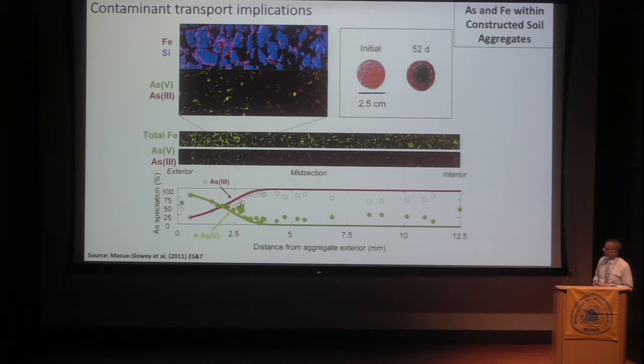As an extension of this work, we could then think about what happens if there's a nutrient or contaminant moving within this system. So these are the same golf ball size soil aggregates of ferrihydrite-coated sand, but now they've added arsenic into this. These are X-ray fluorescence maps, X-ray microprobe maps of iron and silicon on top. Clearly you could see the iron coated the quartz, and then adding arsenic 5 into the system and tracking over time and space the production of arsenic 3 at the expense of arsenic 5.